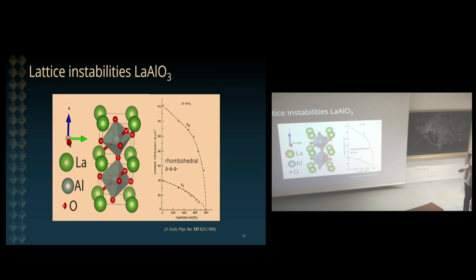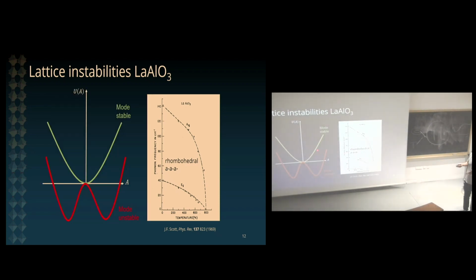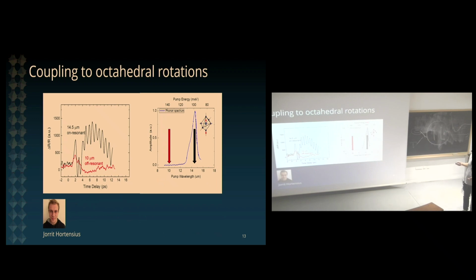So lanthanum aluminate has an interesting structural phase transition from a high temperature cubic phase above 800 Kelvin down to a rhombohedral structure with an A-, A-, A- pattern of octahedral rotation. So these are anti-phase rotations with the axis of rotation along the 1-1-1 direction of LAO in the pseudo-cubic representation. And this phase transition is accompanied by the condensation of two Raman active phonons. One is the A1G mode, and one is an EG mode, which go to zero around 800 Kelvin. So there is obviously a nonlinear lattice dynamics associated with the instability of this particular phonon mode. So there's a possibility to have some nonlinear lattice dynamics here.